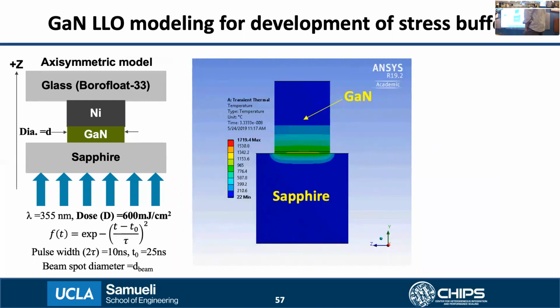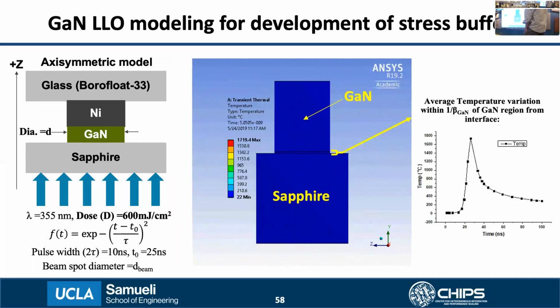So here is an ANSYS simulation of the temperature transients when the light pulse hits. When the light pulse hits, we see that the temperature at the interface rises to around 1800 Celsius and then falls rapidly as the heat is conducted away. Here I've plotted the temperature averaged within the beta-GaN region, which is essentially the penetration depth of the light within the GaN film. You can see how the temperature rises rapidly to around 1800 C when the light hits, and then falls as the heat is conducted out.